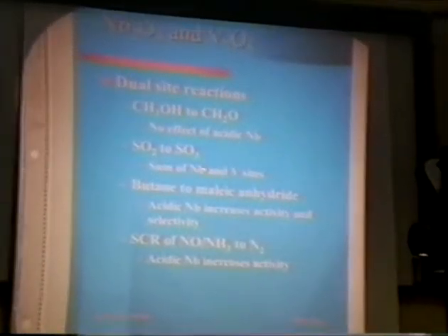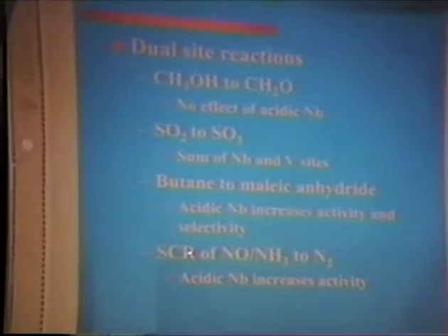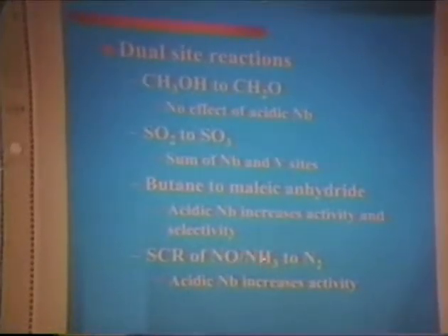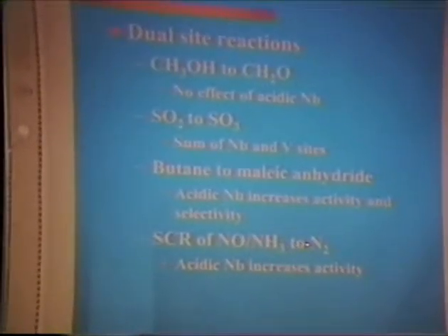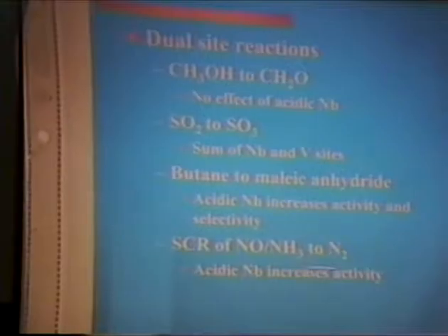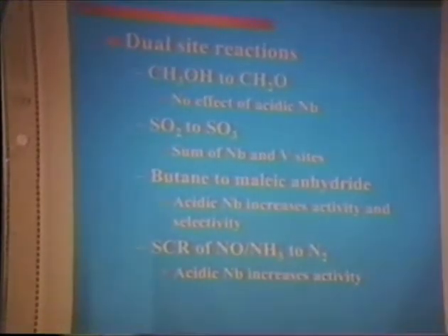If you look at sulfur dioxide going to sulfur trioxide, you do get some contribution from both the acid sites of niobium and the vanadium sites. Butane to maleic anhydride, you're going to see both an increase in activity and selectivity. And if you're looking at selective catalytic reduction of nitrogen oxides with ammonia going to nitrogen, significant increases in activity here. So it has a function, I'll call it a niche player in this area of catalysis.